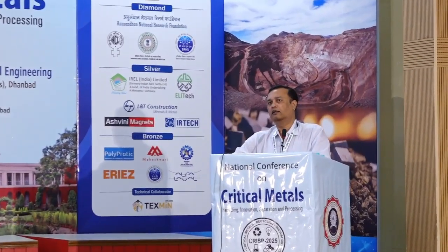Iron provides extra magnetization, increases the magnetic power of the magnet, as well as reduces the cost. So after the 1970s, most of the research was concentrated on increasing the energy product of samarium rare earth permanent magnets, and subsequently the Sm2Co17 magnet was developed that contained around 15% of iron, reducing the total cobalt content from 65 to 58%. In the 1980s, NdFeB magnets were discovered that contained around 75% iron and no cobalt.